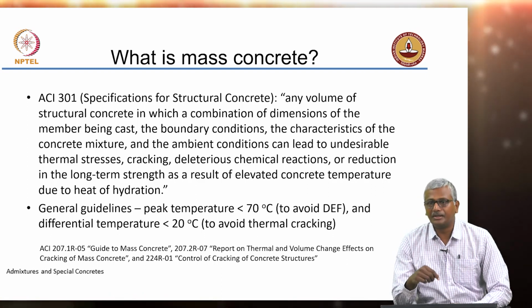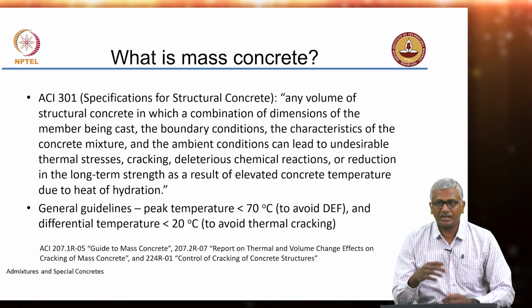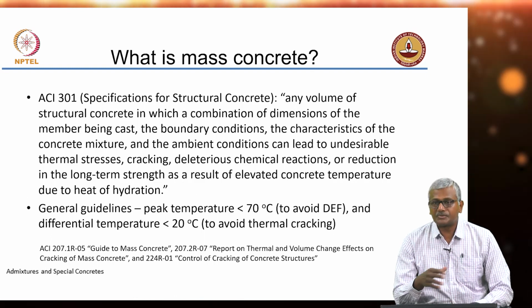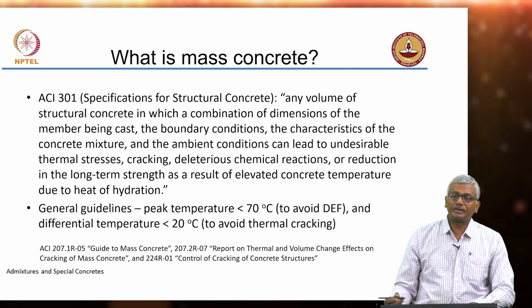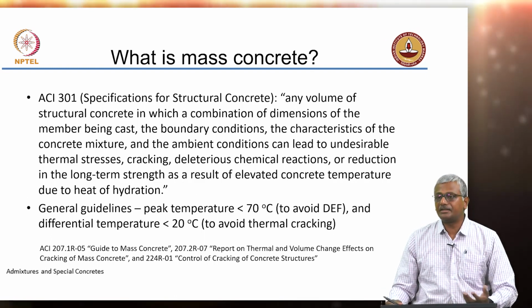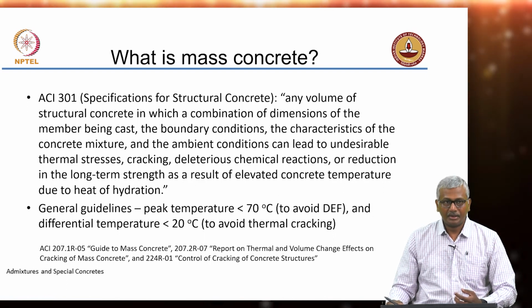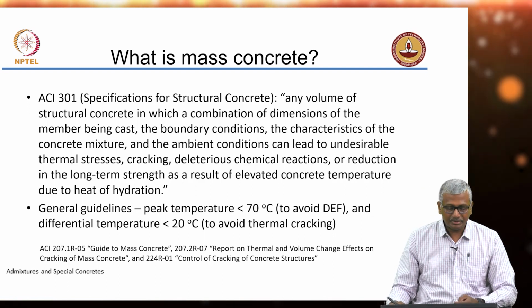Okay. General guidelines that most projects tend to follow is to keep the peak temperature inside the concrete to less than 70 degrees Celsius, which is a very conservative estimate. It is primarily for the purpose of avoiding a chemical reaction known as delayed ettringite formation. Okay. Now, I will talk about that in more detail later.